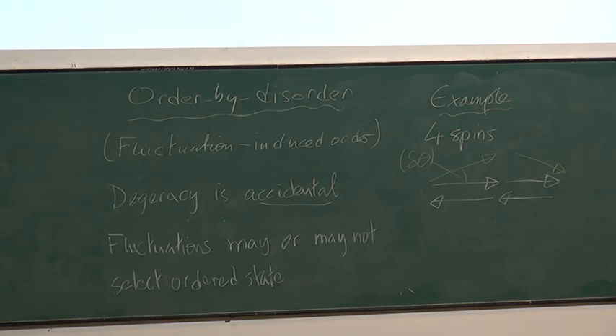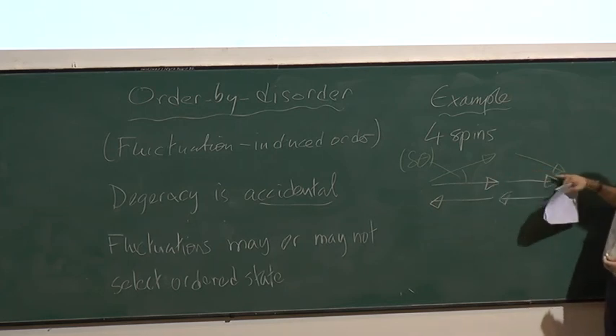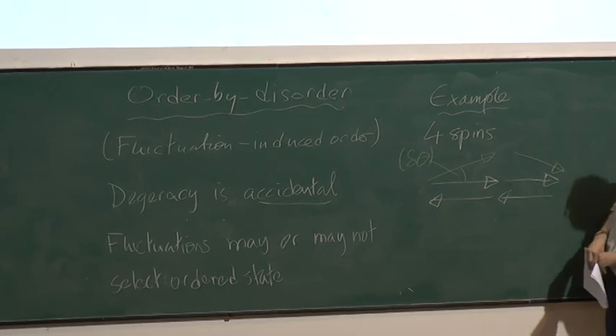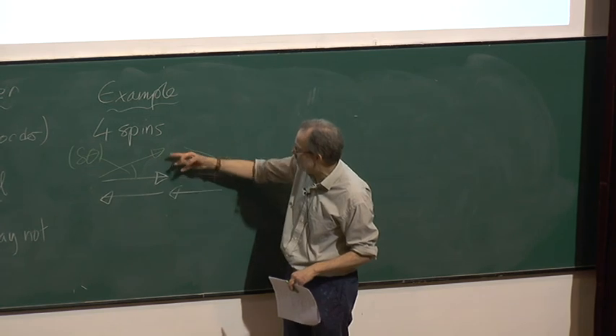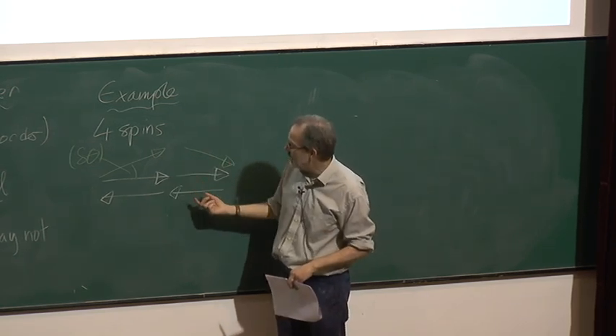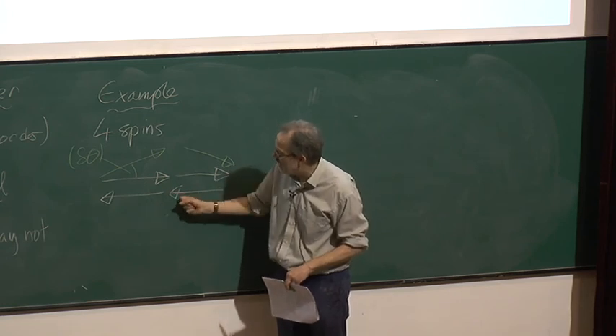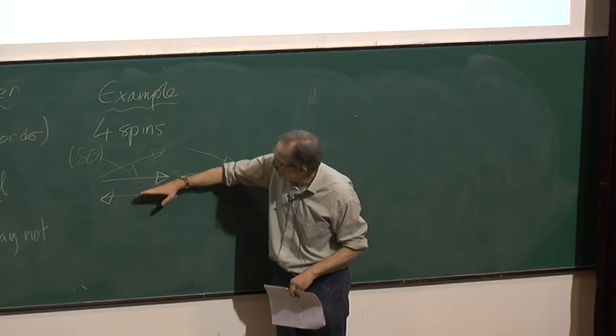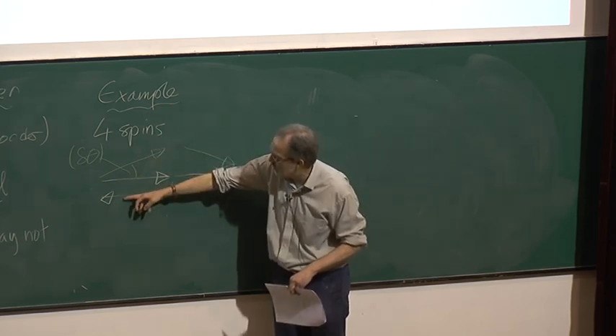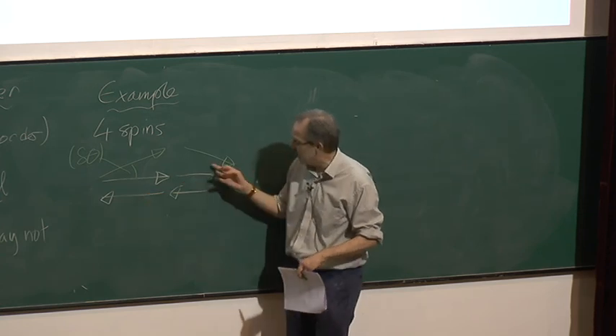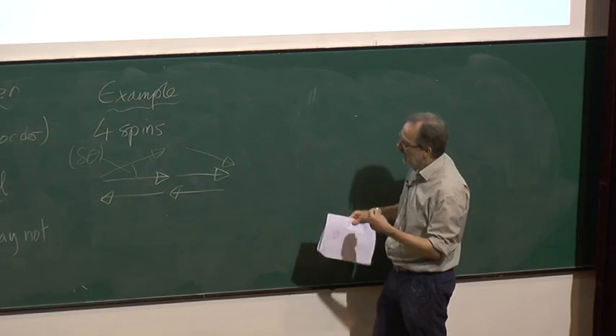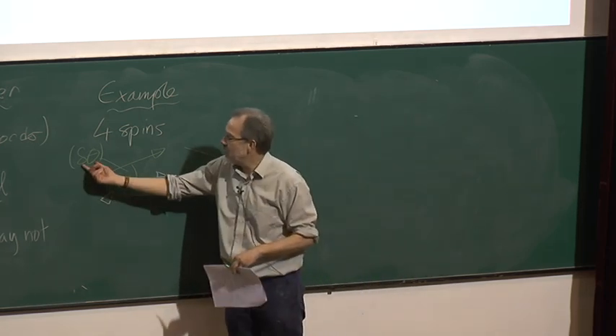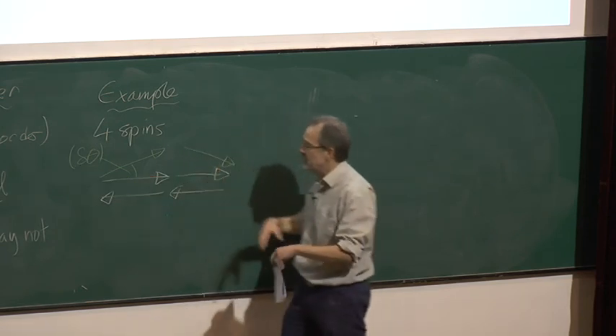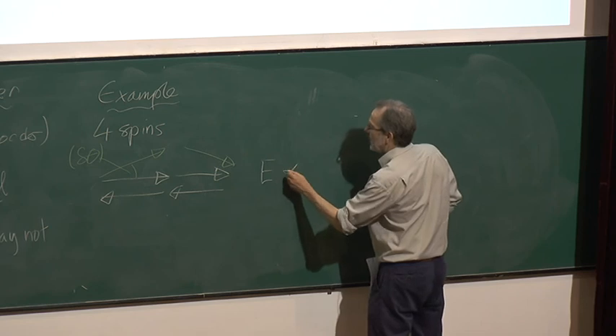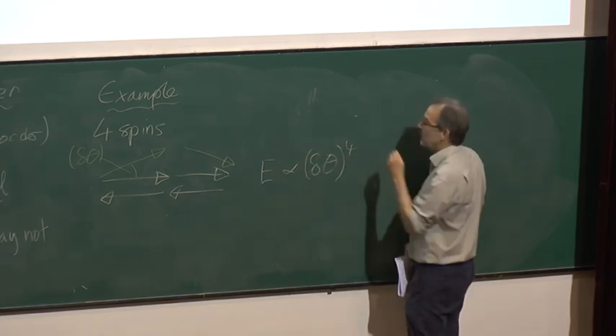The ground state energy, as I said, is the square of the total spin length. If we consider this particular distortion away from the ground state, then the transverse components of the spin still cancel, and we get a net magnetization for the cluster only because the horizontal component of this spin doesn't quite cancel the horizontal component of that spin, and likewise here. So we have a magnetization that grows like the square of the angle, and an energy which is the square of the magnetization, which goes like the fourth power of the angle.